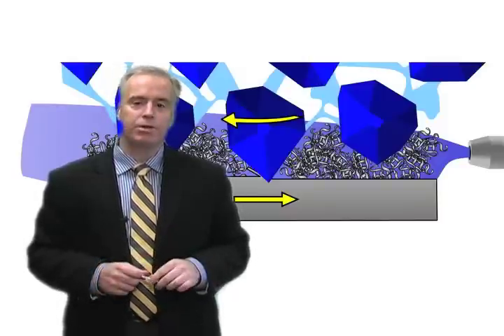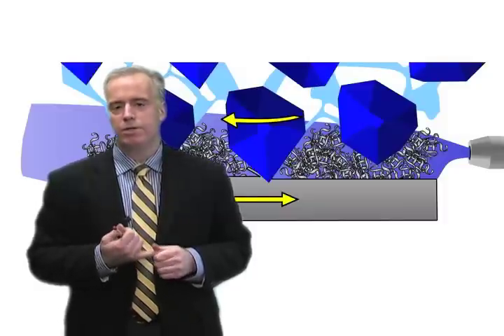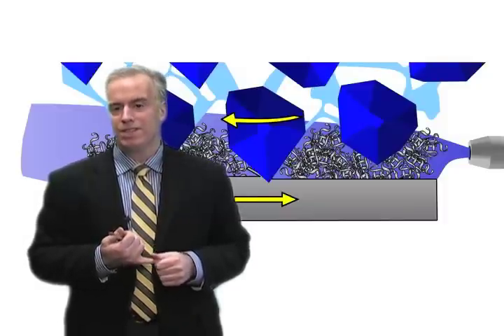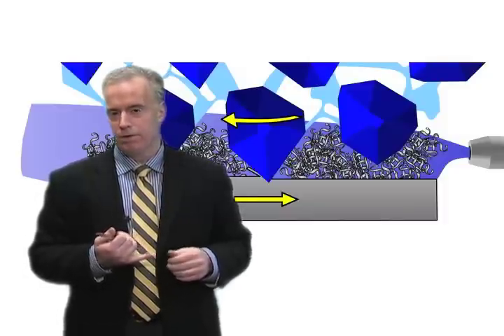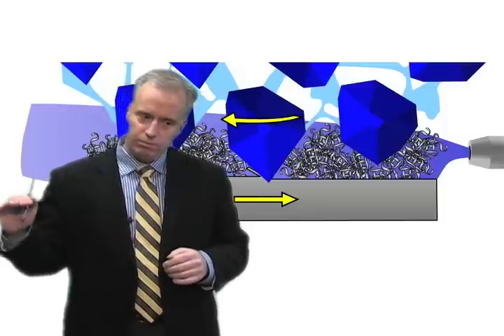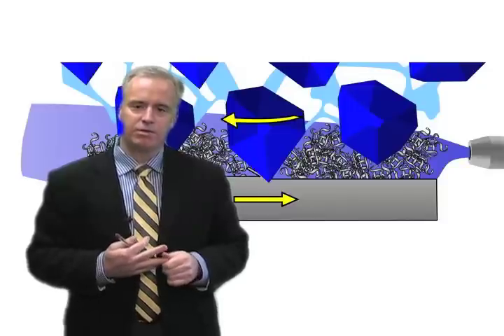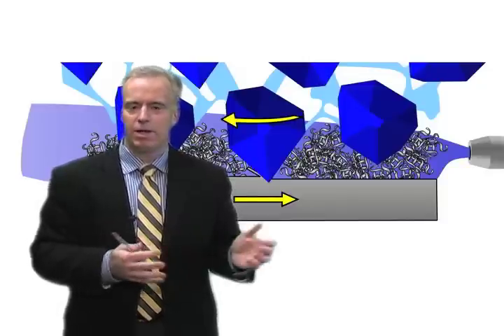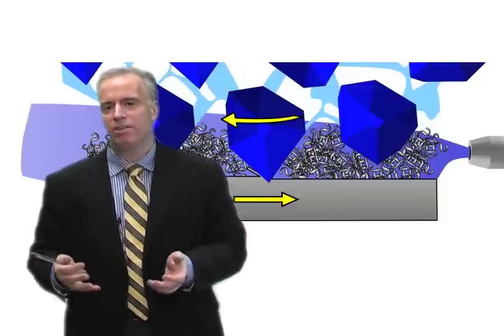Two major things, the two most important things are you want to get your coolant velocity up to your wheel velocity. So if your wheel's going at 10,000 surface feet a minute you want that coolant flying along at 10,000 surface feet a minute getting into the hot spot. Not about flow rates, it's about velocity.